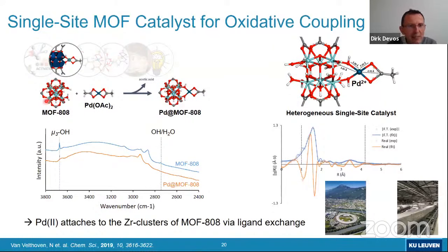I hope you can see all this. This is again this cluster of MOF-808, and I think you see each time these carboxylates that are normally capping, that are surrounding the MOF-808 cluster. Now, if you apply the appropriate pretreatments like solvent washings and whatever, you can remove these carboxylates, and you will then replace the negative charge of the acetate ligand by a negative charge of a hydroxyl group and water. And actually, this is quite a reactive surface. This now acts as a reactive surface very much in the same way as you would have on some oxide materials. And that reactive surface is then going to react, these hydroxyl groups and water molecules react with palladium acetate. And eventually we get something shown like here, where the palladium is actually sitting on two of these hydroxyl groups of the MOF zirconium cluster.